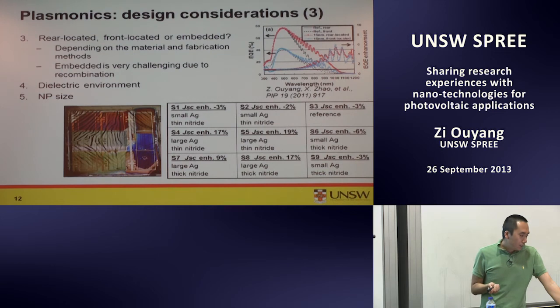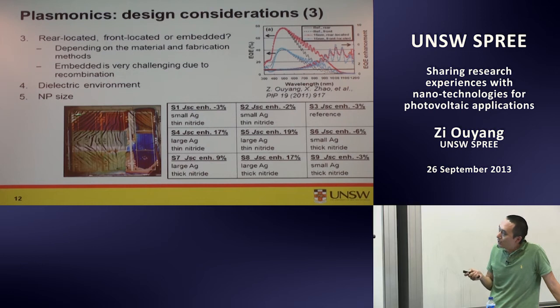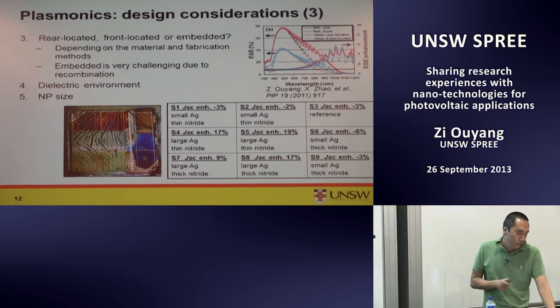And then the dielectric environment. You can use titanium dioxide, silicon oxide, or put it on silicon, or on silicon nitride. You can play around with the environment and the particle size. I won't talk too much about that, but you see this is one solar cell, and one mini module with 9 cells. If you have different silver nanoparticle sizes and different thicknesses of nitride, you can have completely different colors on the surface. That means the resonance of the scattered light is very different. So you have a lot of parameters to play with until you find the optimized one.